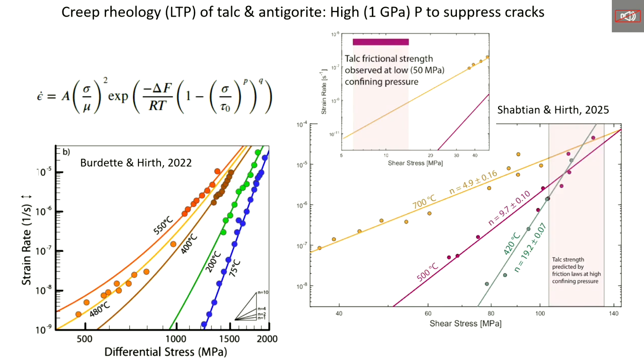It's an indication of low temperature plasticity. And you couldn't get these data at low pressures because the friction coefficient is so low. The shear stress is only 10 megapascals. At 700 degrees, her highest temperature, the strain rate is 3 orders of magnitude less than the frictional strain rate that you're applying. So it's like the technology in the lab, despite doing these experiments for 50 years, new things keep coming on, and you can apply them and get new data, which is really cool.